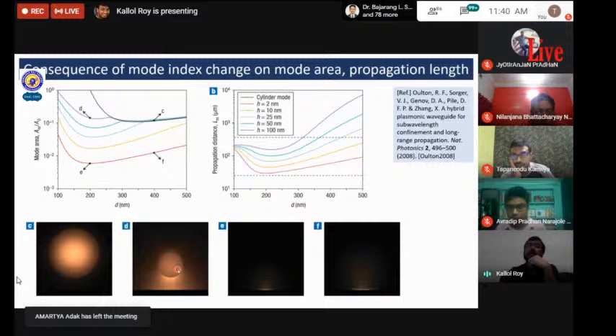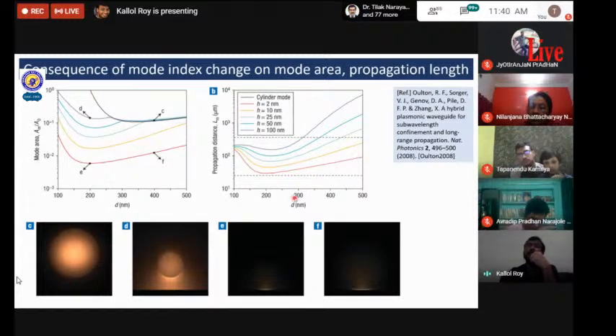And definitely it has a consequence. Although the light is getting confined at the metal dielectric interface, there is a loss that comes with it, and because of that you can see the propagation loss is high. For example, if we take a particular d, say 500 nanometers, and compare different gap sizes, say a 100 nanometer gap versus a 2 nanometer gap, you can see that the propagation length is very different. It changes by almost 2 orders of magnitude.